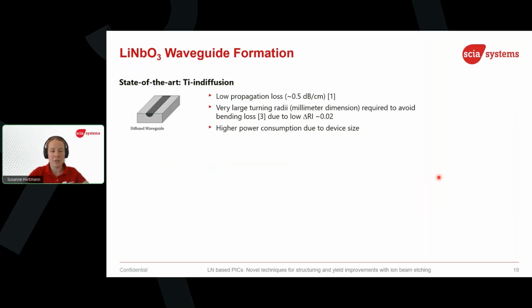The state of the art is so-called titanium in-diffusion. In this case, we have lithium niobate all over the place, and on top of this, there's a structured area of titanium, which is then by annealing diffused into the lithium niobate. By this, we have a local change of refractive index, which defines our waveguide. However, this change of refractive index is relatively small, so we still need very large turning radii for our devices to avoid bending losses. This means that we have a huge device size and higher power consumption.